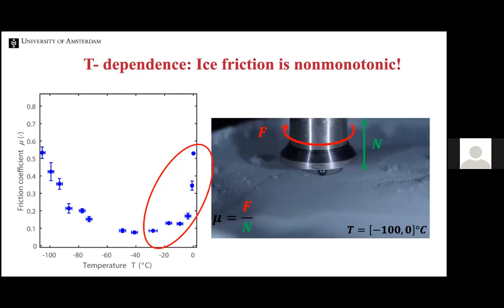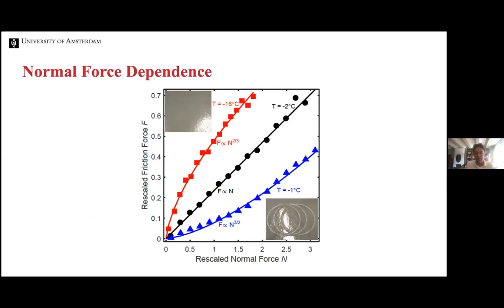Okay, but later on you comment that the dependence of the friction force versus the normal force is not linear, so the plot of the friction coefficient should depend on the normal force. Yeah, so this plot you mean? Yes. This gives a range of friction forces for the blue and the red curves. What we do is we simply give an error bar from the slope at the beginning to the slope at the end. But the variations of friction force are much larger than the curvature of these lines.